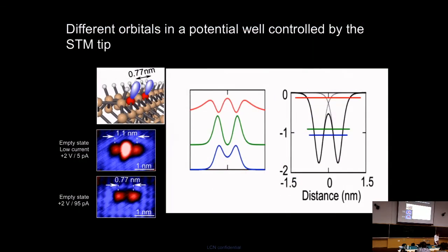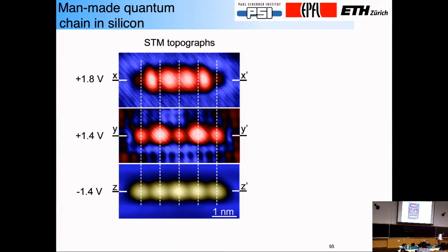Now, this scheme can be generalized to look at chains of atoms. I can make chains of dangling bonds, model atoms, using the STM again. Here I'm showing you a case where you can see there are 1, 2, 3, 4, 5 atoms. For instance, at a bias voltage of 1.4, going into the conduction band, what I'm seeing here is no longer homogeneous. I see small density, high density, small density, high density. So it breaks the periodicity that I had when I'm just doing topography at minus 1.4 volts.